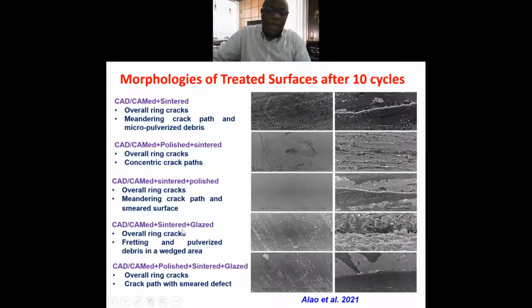For the CAD-CAM sintered glaze, you can see the ring cracks, and you can see the fretting and then pulverized debris in a wedged area. Then for the CAD-CAM polished sintered glaze, you can see the ring crack and then crack path with smeared defect.